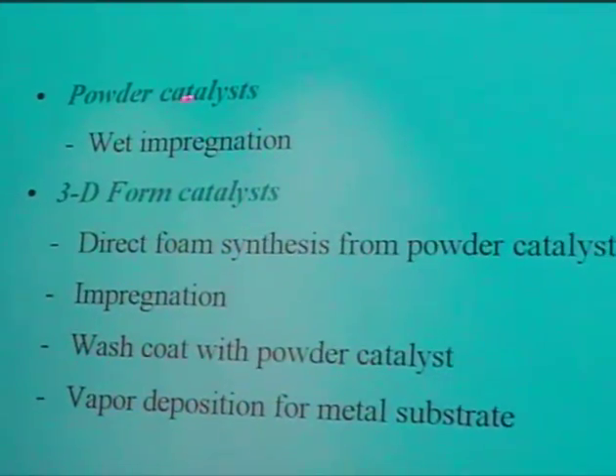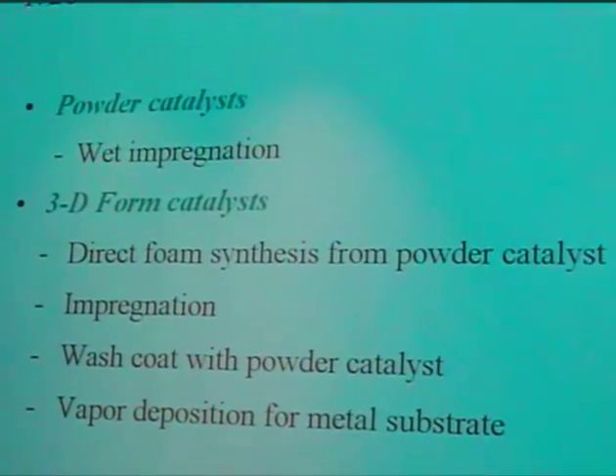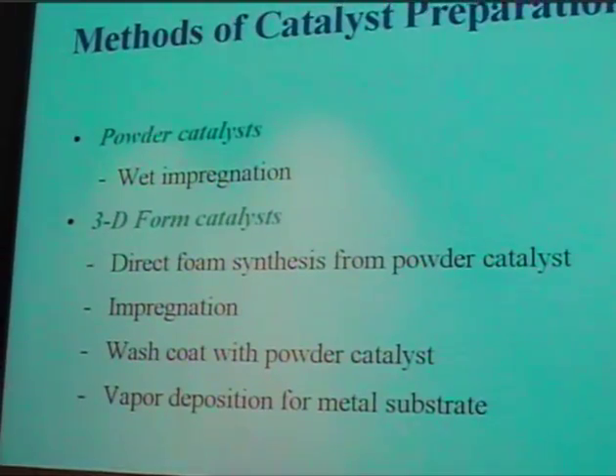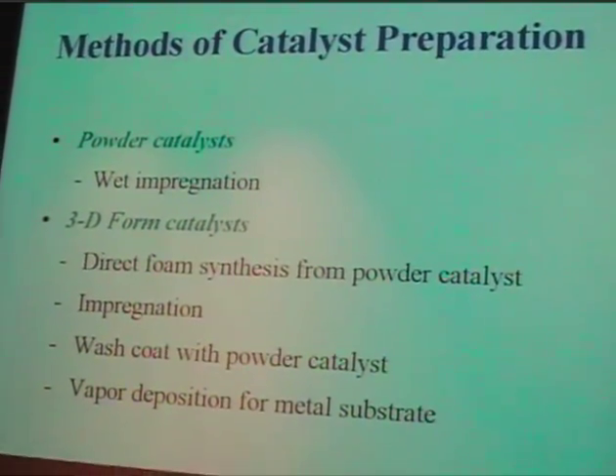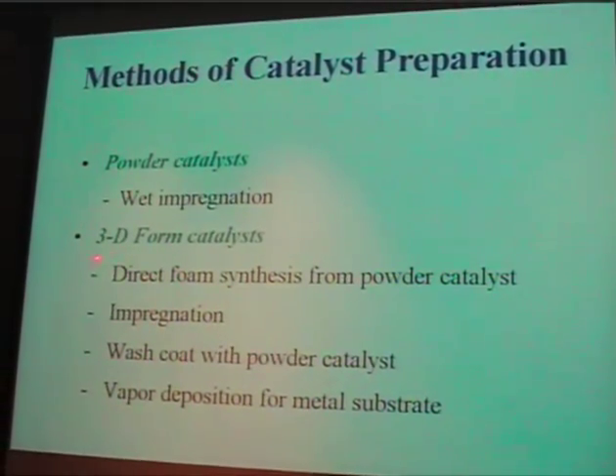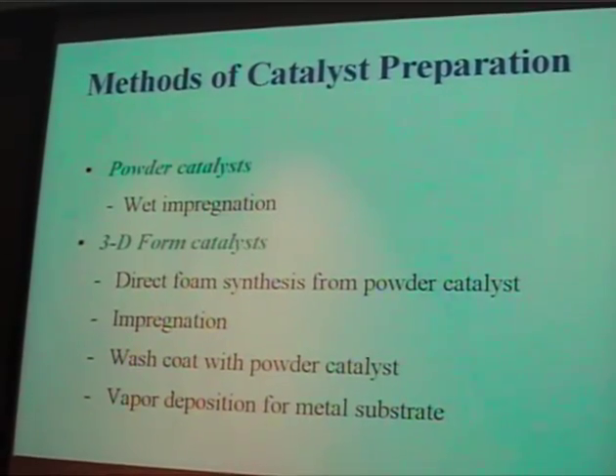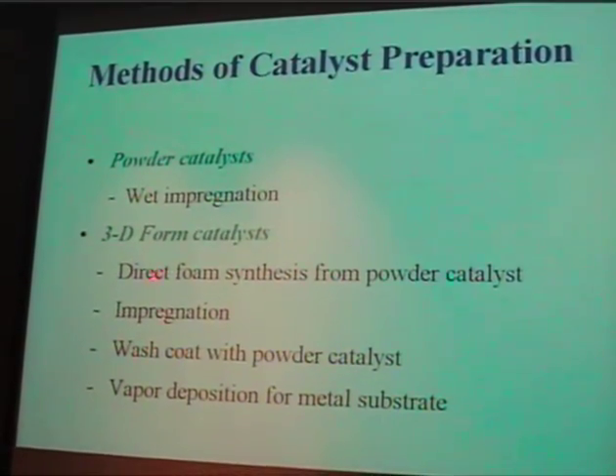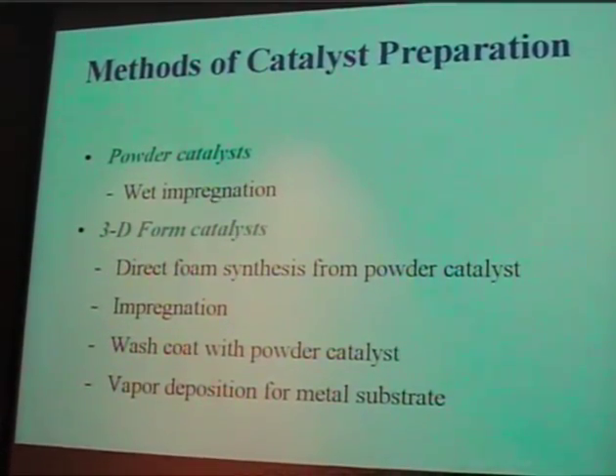So it was rather straightforward preparation. We used wet impregnation. In our case, we did a lot of our work with MgO, and we also prepared catalysts in three-dimensional forms, and you'll be hearing a little bit about that. We could use a foam and impregnate it with a powder and then burn out the foam. We could impregnate the 3D structures, wash coat them. We even did vapor deposition studies.